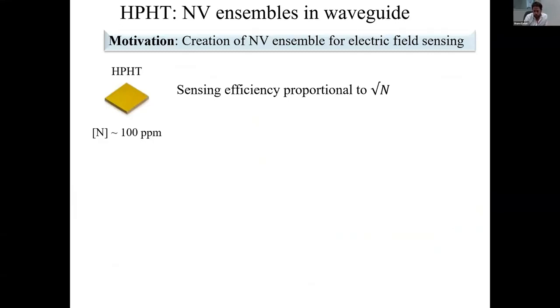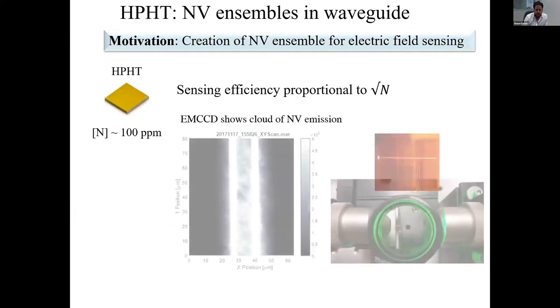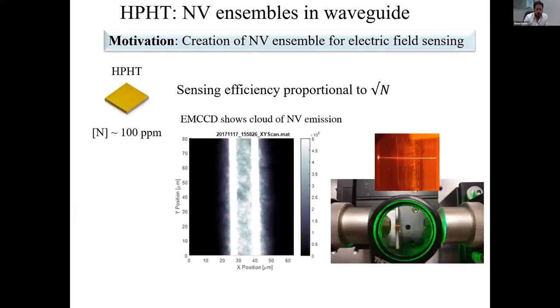Sensing efficiency is proportional to the square root of the number of NV centers. And actually, this is where our initial result is very, very promising. This shows an EM-CCD image of the NV emission from one of these waveguides. So this is taken from overhead from one of these type 2 waveguides. You see the two damage lines formed by the laser. And in the middle, you see this very bright cloud, which we anticipated was due to these NV centers, due to the filtering we applied. You see that also on the right, where we have a nice filter, and we still see this nice streak of emission from the characteristic wavelength window of NVs.